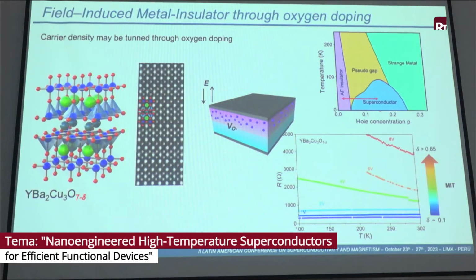And in particular in YBCO, what we have is the possibility to change this axis, the hole concentration, by changing the oxygen in the system. This is the TEM image of a YBCO layer, and we have here the structure of the YBCO, which is YBa2Cu3O7-δ. This delta is the amount of oxygen that we have in the system. By changing the amount of oxygen, we change the amount of carriers in the copper plane, and we change the axis of the hole concentration here.